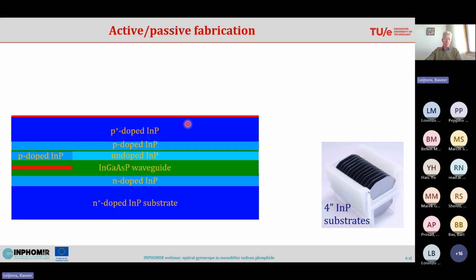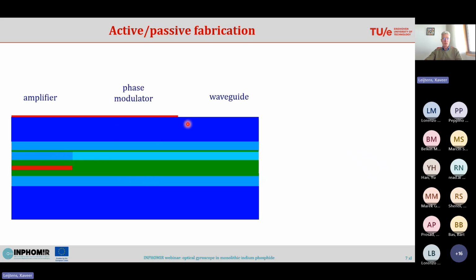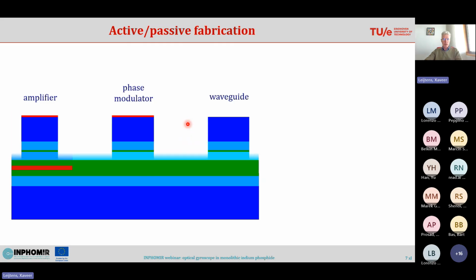So for making these, we first remove the contact layer where we don't have active components, and then we etch structures, waveguides for the amplifier, the phase modulator, and the waveguide. So we etch the waveguides, and now what we have is a structure that provides amplification, a structure which, reversely biased, well, after we put the metal, can provide an electro-optic phase change, electrorefraction, and we have a waveguide for guiding the light.